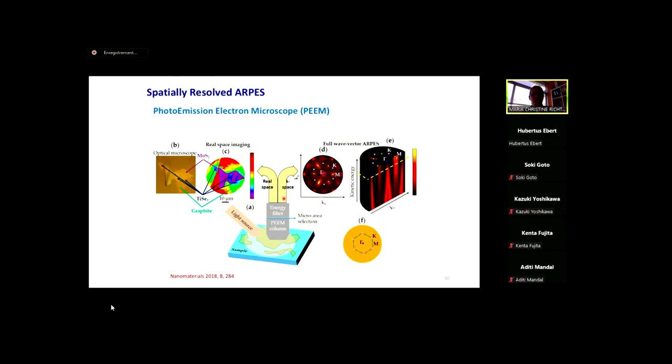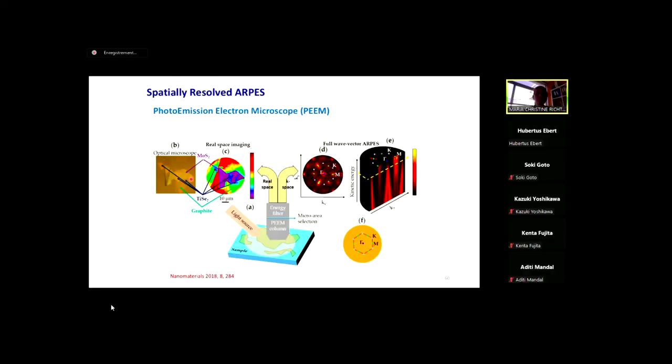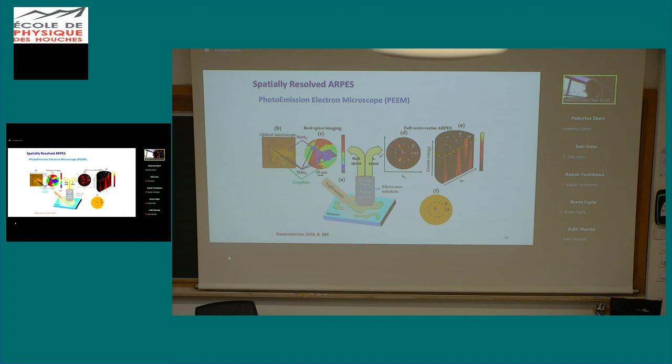Which is sort of schematized here. You have your sample, and from that you form with the photoelectrons a real space image, but at a certain energy, you filter the energy. So you get the real space image for a certain energy of the photoelectrons, and then you scan the energy, and that means that in this real space image, for each pixel, you have a whole photoelectron spectrum. And that gives you the occasion to choose the area of interest on your sample,